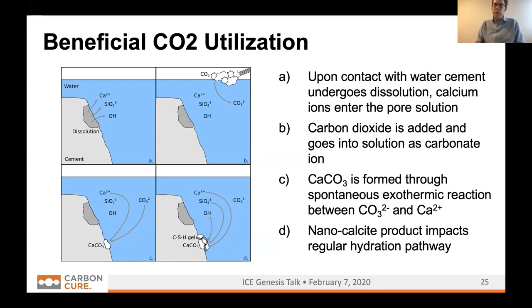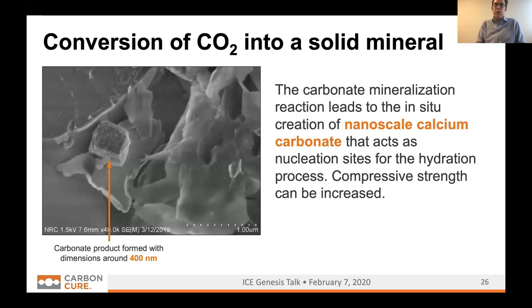Once the carbon dioxide enters the system, the CO2 will form a carbonate ion in solution. Now, once the calcium and carbonate ions are both in the same solution, this is the most thermodynamically stable place for the calcium and carbonate to go. So we form calcium carbonate. That removes a little bit of calcium from the system, but ultimately, once this calcium carbonate has been formed, the rest of the hydration of cement can continue as normal. So you will form calcium silicate hydrate gel, calcium hydroxide, ettringite, and so forth. Essentially, the CO2 is now converted into a solid material.